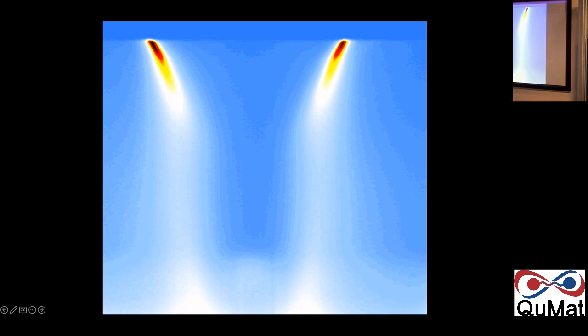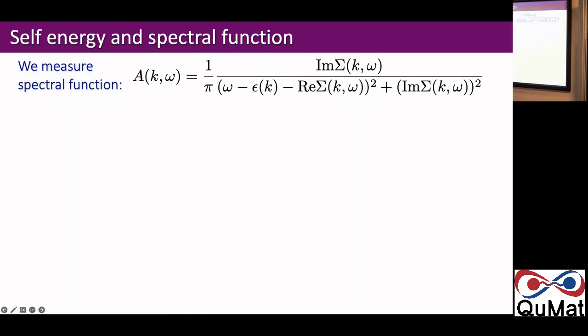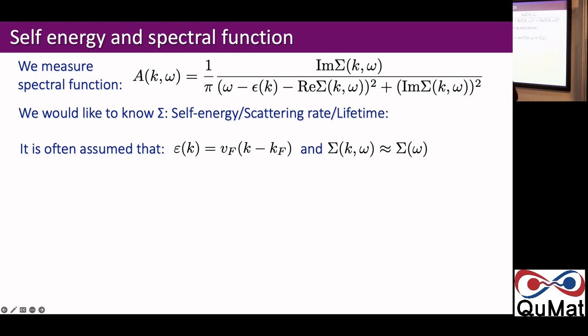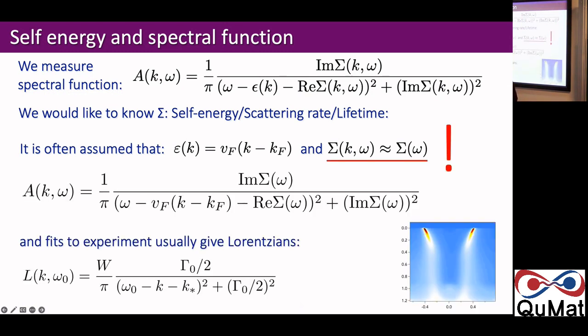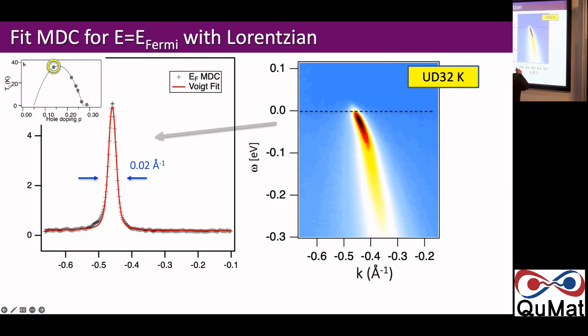The broadening itself, that you can't see, so there is broadening of the peak. Yes. Is this a quasi-particle effect? The broadening of the peak is telling us it has a finite lifetime. Right. So here at the Fermi energy, it's as narrow as it can get, and if we go down here, let's say we go to 0.1 eV, this is going as linear in frequency. So this will then be some peak.